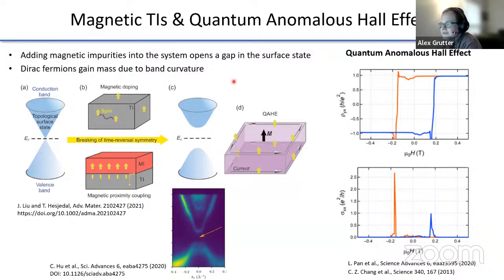And once you've done this, once you've broken time reversal symmetry and you cool down the system to really, really, really cold temperatures in the sort of hundreds of millikelvin regime, what you get is quantized edge conduction. And that is the quantum anomalous Hall effect, which is characterized by a Hall resistance of plus or minus 1 h over e squared, and a longitudinal conductivity of 0. So this state is very interesting for a whole host of different applications in sort of quantum electronics.